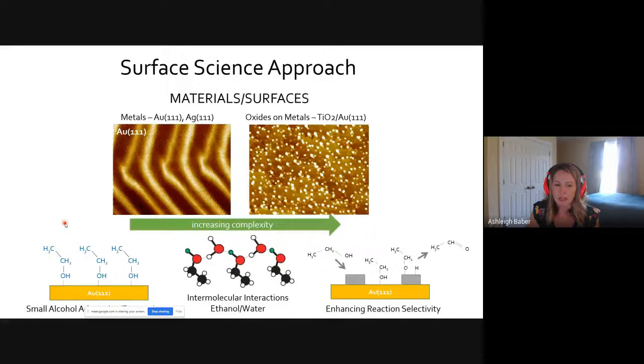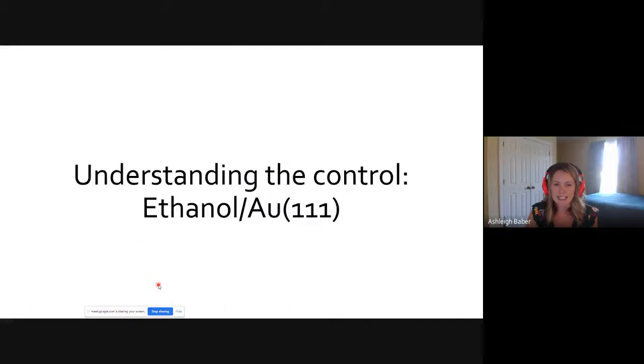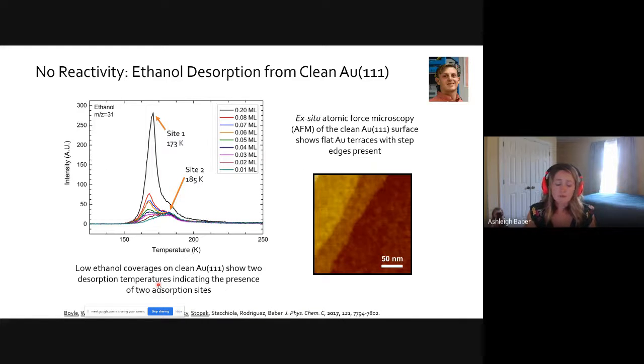To where we are jumping off, I'm starting from, again, just the fundamental side. But I really find even just looking at simple alcohols on gold to be fascinating. So let's first of all understand the control before we start making things more complex. One of the first experiments done in my lab, David Boyle, who has since graduated, looked at ethanol on gold 111. We're not the first people to do this by any means, but we did look at such low coverages of ethanol on the gold 111 surface that we saw several peaks appearing, and that had to do with the adsorption of ethanol on different sites on our surface.